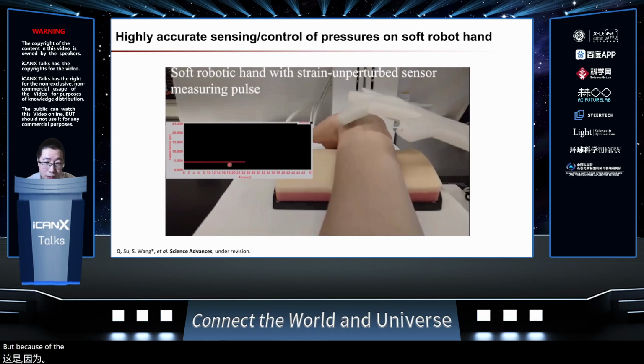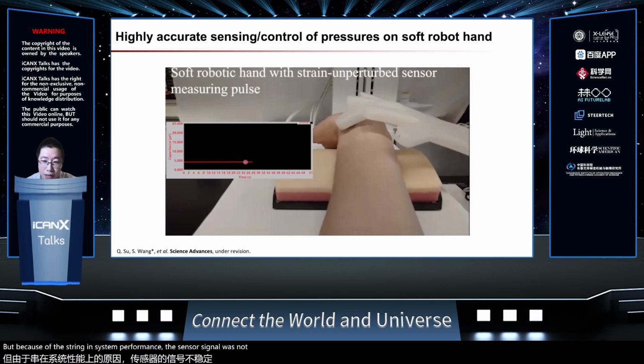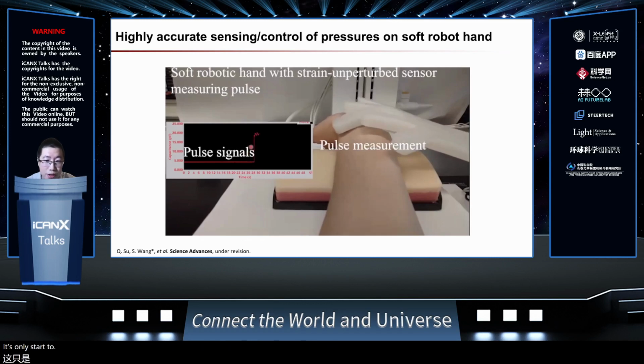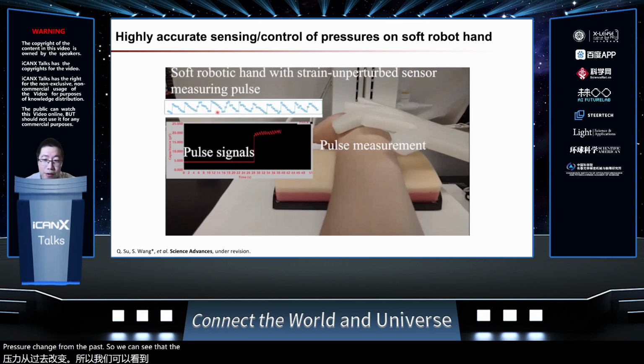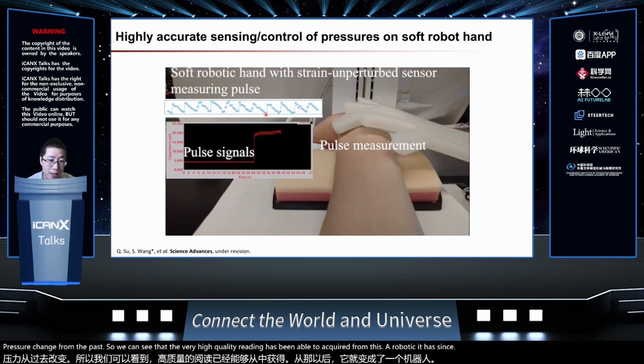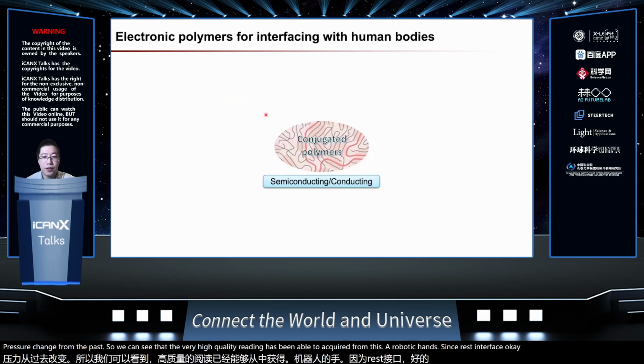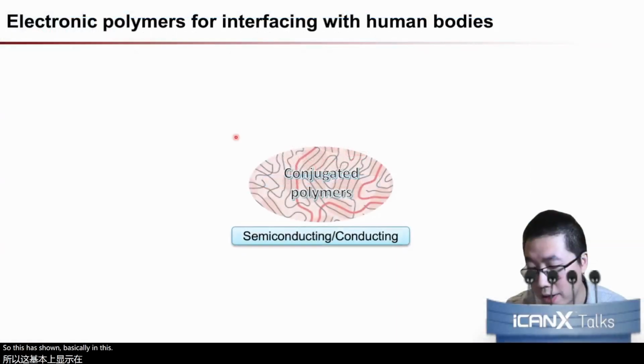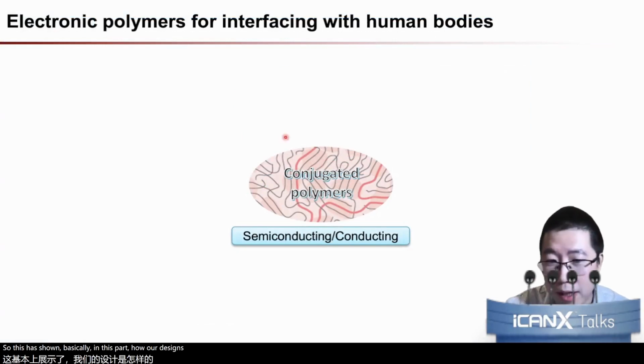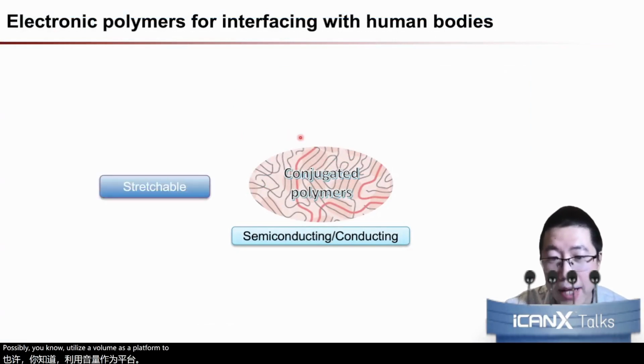But because of the strain insensitive sensor performance, the sensor signal did not change. It only starts to change when the sensor gets onto the human body and there is a pressure, and then starts to record the pulse waveform from the very subtle pressure change of the pulse. So we can see that a very high quality reading has been acquired from this robotic hand's sensorized interface. Okay, so this has shown in this part how our designs can utilize a polymer as a platform to combine the stretchability with the semiconducting or conducting property.